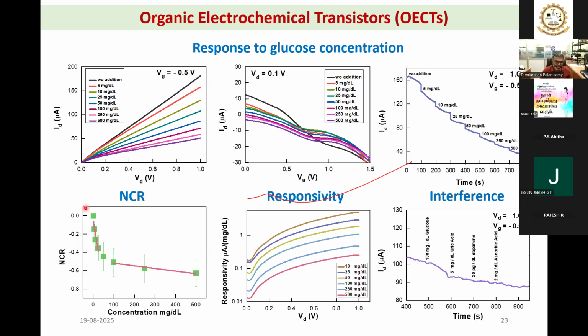And the extracted values are giving the normalized current ratio. This normalized current ratio tells you how much your sensor is responding per unit amount of glucose concentration. Okay. And you can see here, this is the responsivity curve. Your y-axis is microampere. The microampere current change per 1 milligram per deciliter change in concentration. Okay. And you can see as good as almost 1.8 or 1.9.